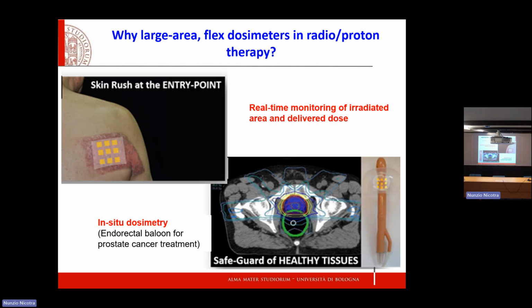Patients can develop huge skin rashes, because there is not a complete control of the area that is exposed and of the dose that is actually delivered. Of course, there is a control, but you can't do it in real time, because if you put a silicon detector, it would absorb all the radiation, and then you would have to redo the measurement again. Also, the silicon detector is not able to cover such a large area. So you won't be able to map the actual area that is irradiated and the dose that it has received.